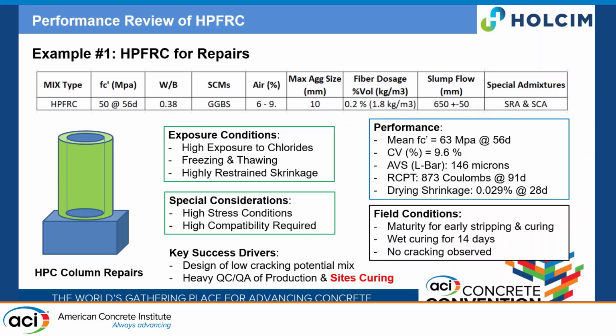So you need to work around how you can reduce the stress and increase the compatibility of the repair. For that, we have a 50 MPa mix. We use an SCC consistency. We added some fibers. What the fibers do is also bring down a little bit your MOE, your modulus of elasticity. So it makes it a little bit more ductile, but less brittle between the repairs and the core material. So we have been able to achieve pretty good consistency on this project. We also implemented maturity to have early stripping and early curing, because we integrate some shrinkage compensating admixture. And when you add this admixture, it's critical to add early wet curing. And that was a good success.